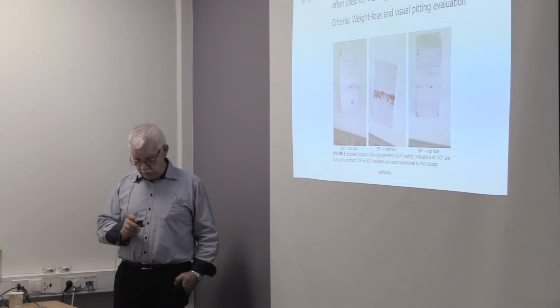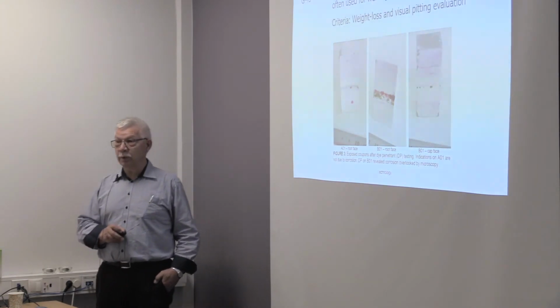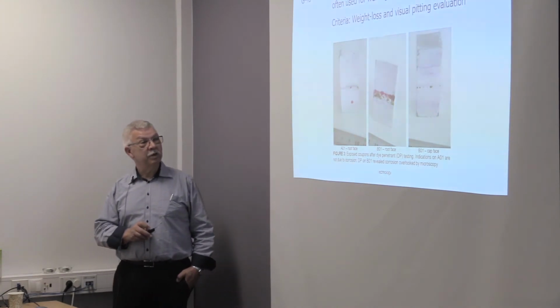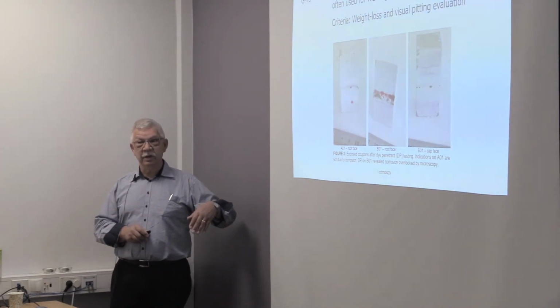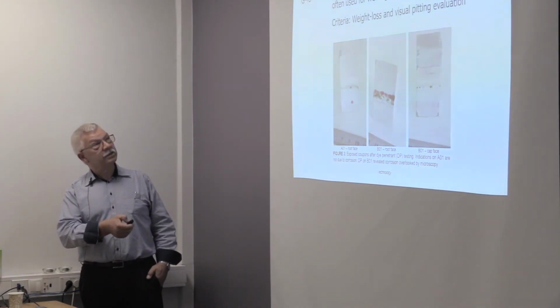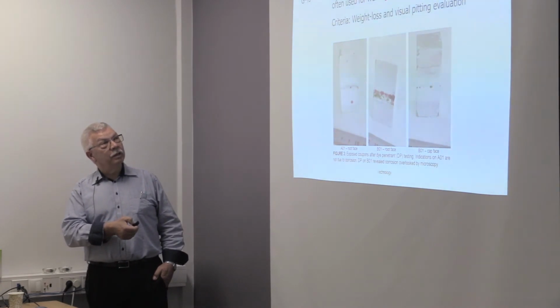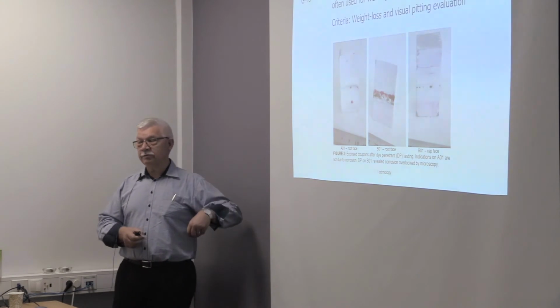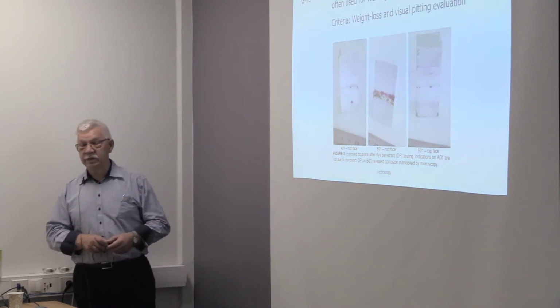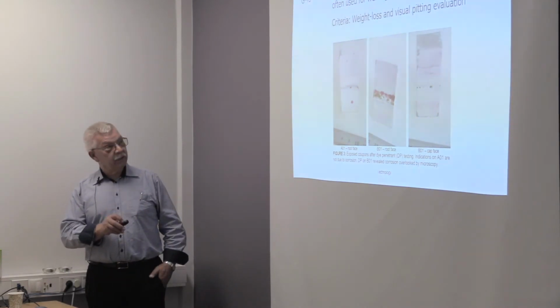The G48 is a standardized test used very much for welding procedures in stainless steel and other corrosion-resistant alloys. We define for a certain material that it has to be able to withstand this ferric chloride test to a certain temperature, and depending on how successful the weld has been, it will fail or it will pass this test. And this example shows a sample which has passed.